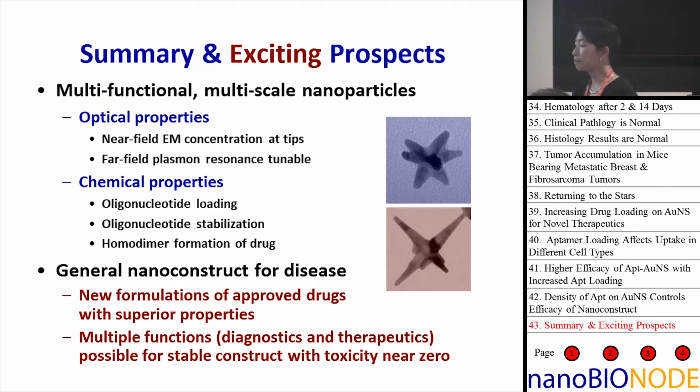And then in terms of the other thing that you can do, because you notice, I mean, this is sort of full disclosure on all particles, right? There's a distribution in shapes, even within these types of things. So we have been in collaboration with Mark Hersam using this technique called density gradient ultracentrifugation. So what you can do is based on the density, based on the number of branches and things like this, you can separate out in like this large centrifuge tube. And so the different particles will have different bands of color. And so then if you just take that band using a fractionator, then all of those will be very pretty, not monodispersed, but very good in terms of the dispersity.